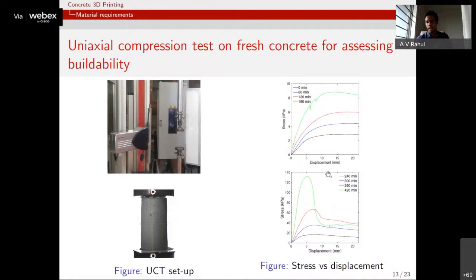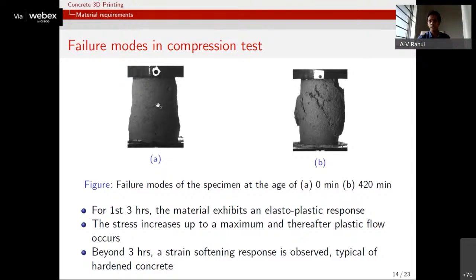The other aspect is the type of failure also. Initially you see an elastic behavior and then a plastic type deformation after that. So it's mostly an elastoplastic material early on, but as you proceed to higher ages, as you go to 420 minutes, for example, you see more of a strain softening type behavior, which is most closely associated with that of hardened concrete. You can also see that in how the specimen fails. This is how a specimen would fail at 0 minutes. It's mostly a very plastic material. It can have some elastic strain carrying capacity, and then after that, it fails by undergoing indefinite plastic deformation.